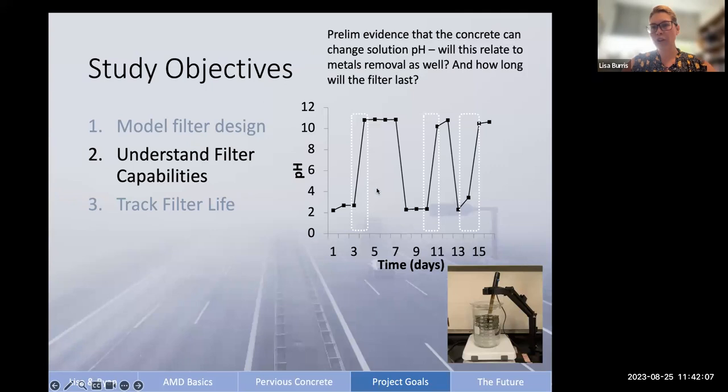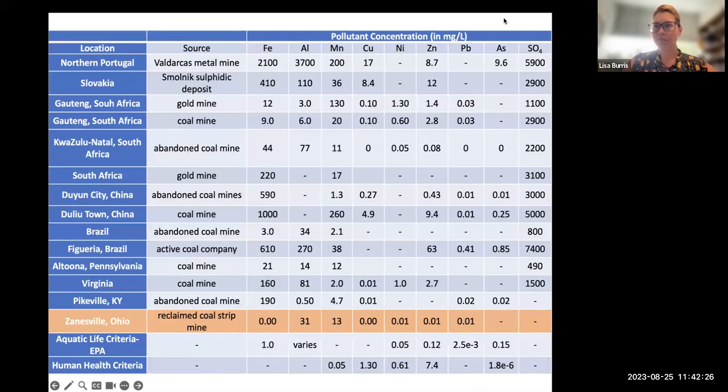And we saw it over and over. So the drop in pH is where we changed out the solution and then waited again to see if we could re-increase the pH or if the cement and the alkaline component of the cement had been consumed. And so you can see we did it 3 times in a row. And so from here, we began to pursue funding and look to investigate this a little bit more.